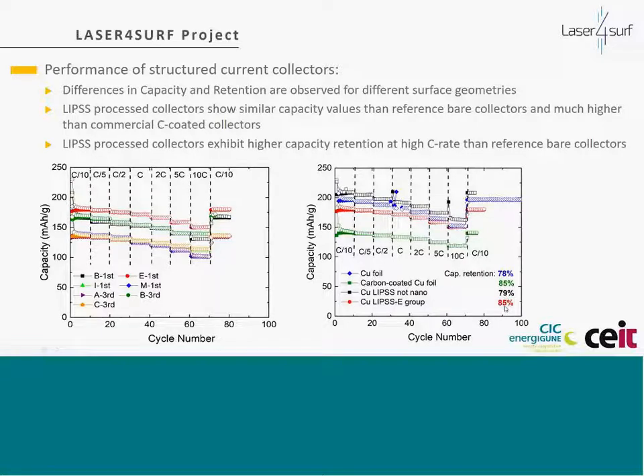So you can see here that the electrodes processed with the laser have the same capacity retention as the carbon coated foil. So we could replace the coating process with a laser process. And you can also see that we have a better capacity value for this laser processed current collector than for the carbon coated one, which is, let's say, the standard or the target for this application. So by inducing these structures on the surface, we can get better capacity values as well as maintain the capacity retention of the technology used today for the fabrication of batteries.